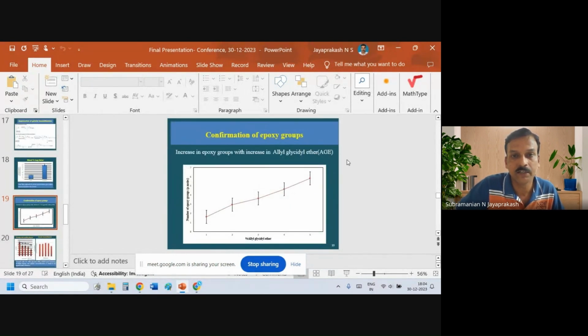And we also did the confirmation of epoxy groups. So we found that an increase in epoxy groups happened with an increase in allyl glycidyl ether. In this graph, you can see the percentage of allyl glycidyl ether increasing, and also you can see that as the percentage of AGE, that is allyl glycidyl ether, increases, the number of epoxy groups also increases.